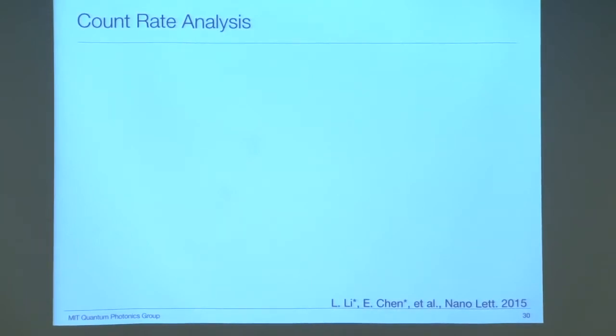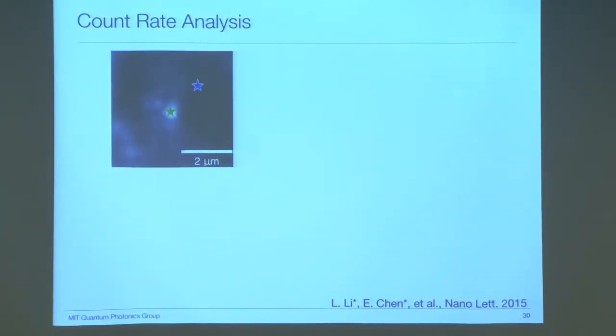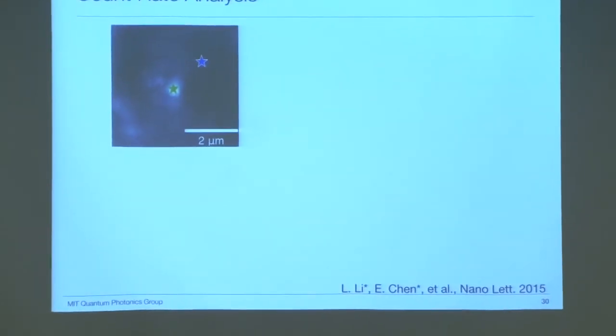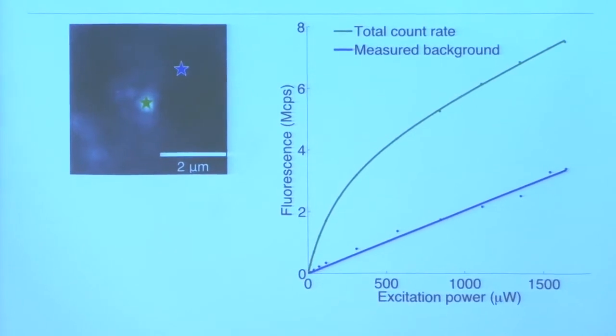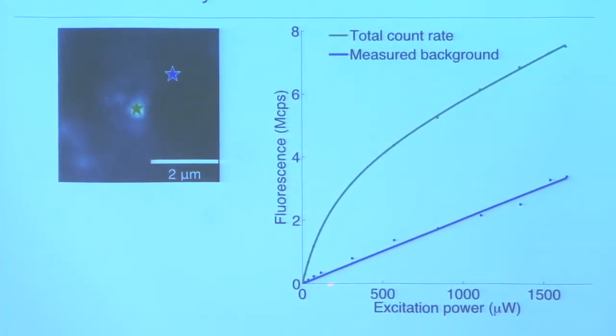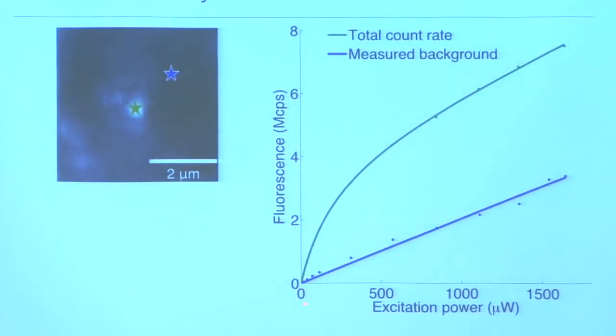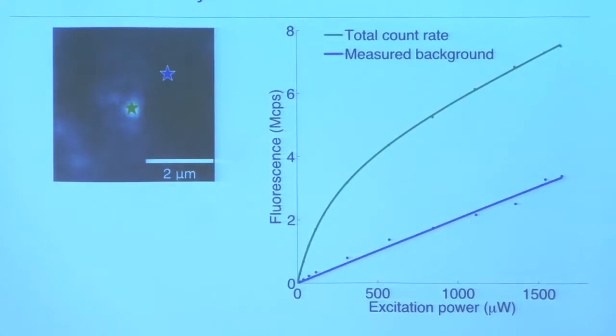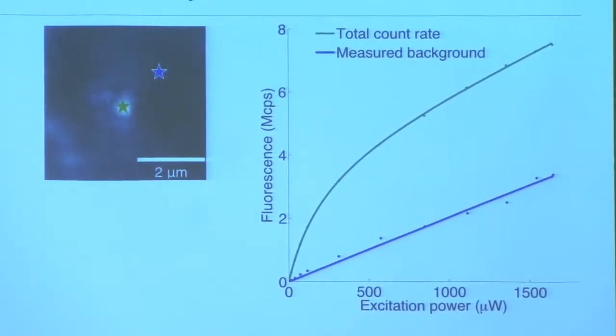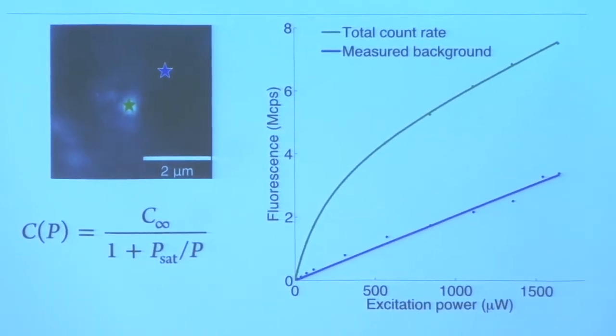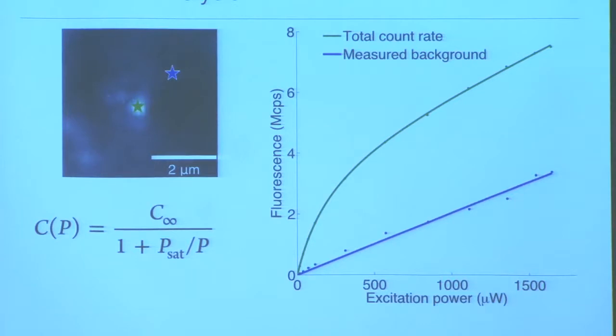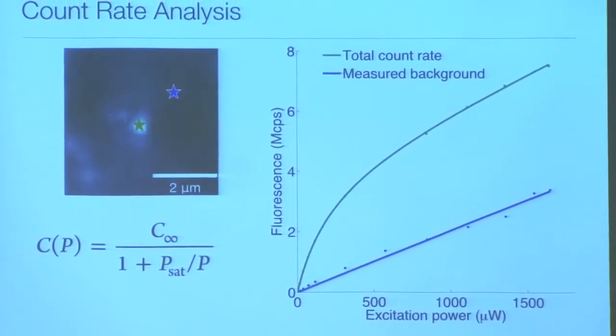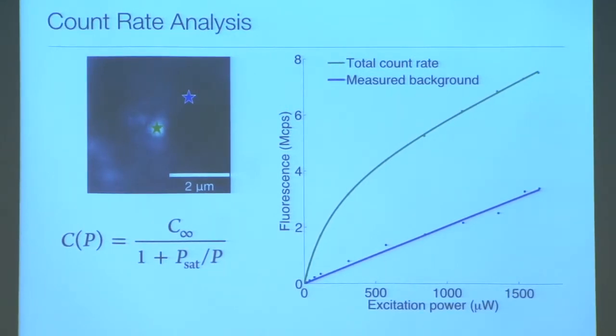To estimate the saturated count rate from a single NV center inside of a bullseye, we have measured the count rate as a function of excitation laser power. This blue line is measured here, which gives a linear background line. And the green line is measured at the NV position. We subtract the background from the total count rate. Then we fit the subtracted count rate with this saturation curve fitting equation. This is commonly used in quantum dot and NV communities.